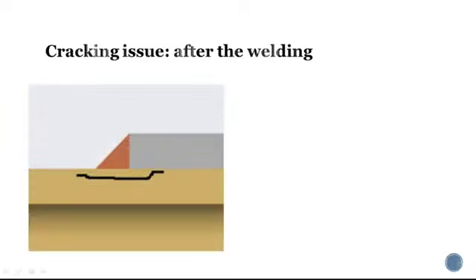One more disadvantage of uneven cooling without proper post-weld heat treatment is the cracking issue, and that happens right after the welding, within 24 to 48 hours. As you can see in this weld cross-section area, because of the residual stresses generated between weld metal and base metal, especially at the heat affected zone, these stresses try to pull the weld metal and base metal in opposite directions, and because of that a crack is generated, or there is a failure underneath the weld at the heat affected zone.